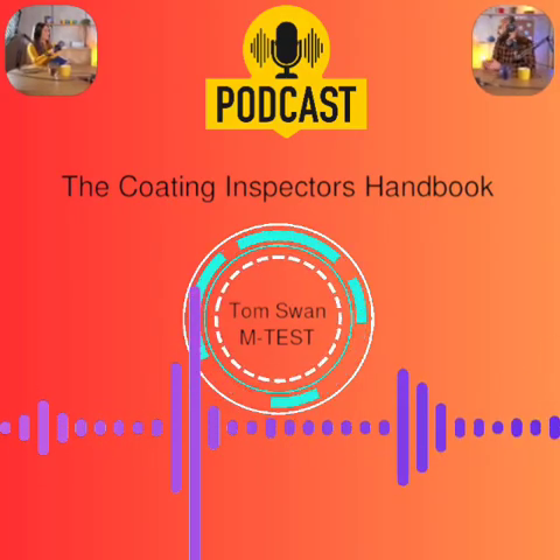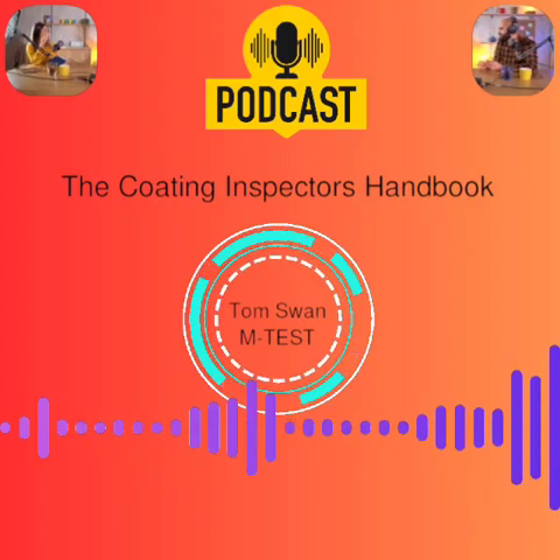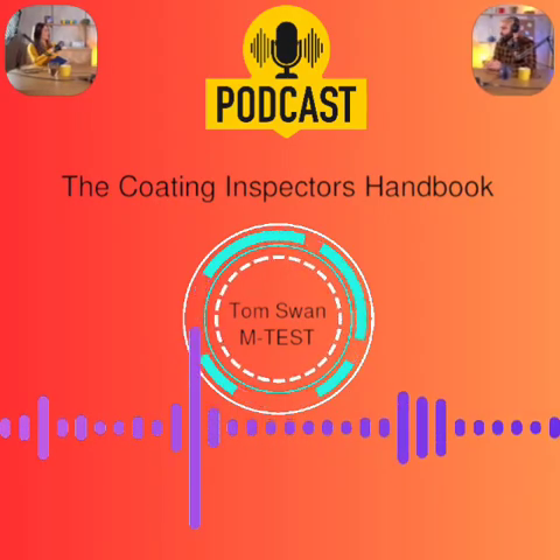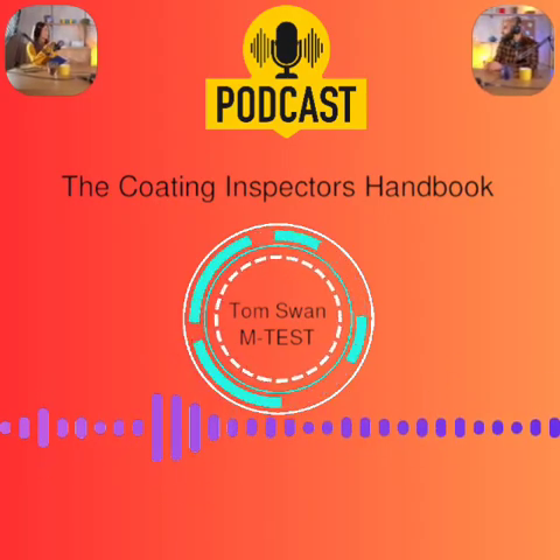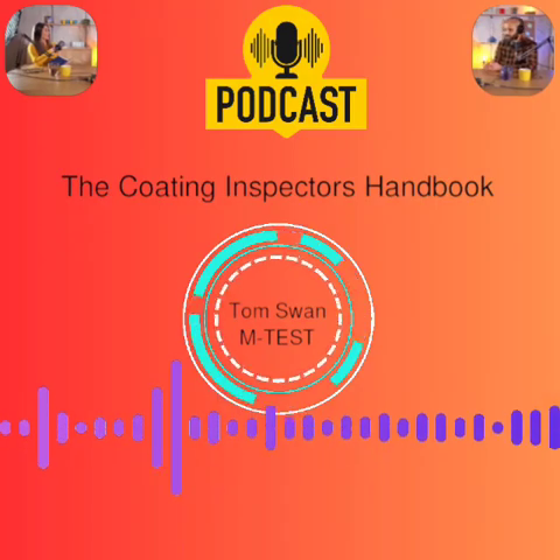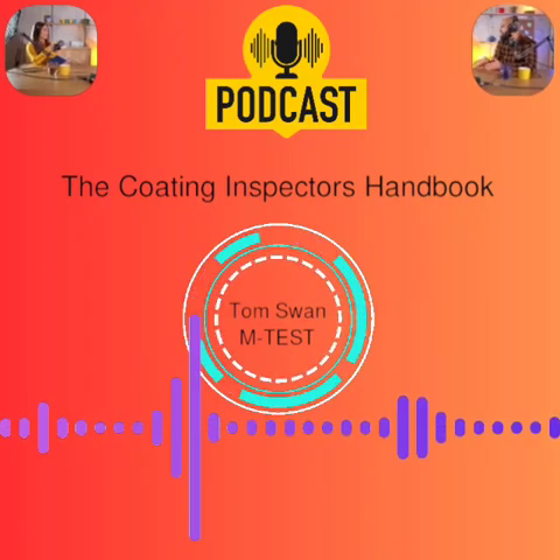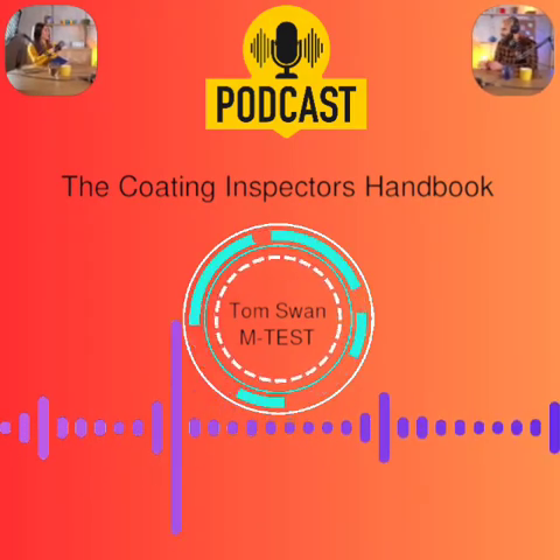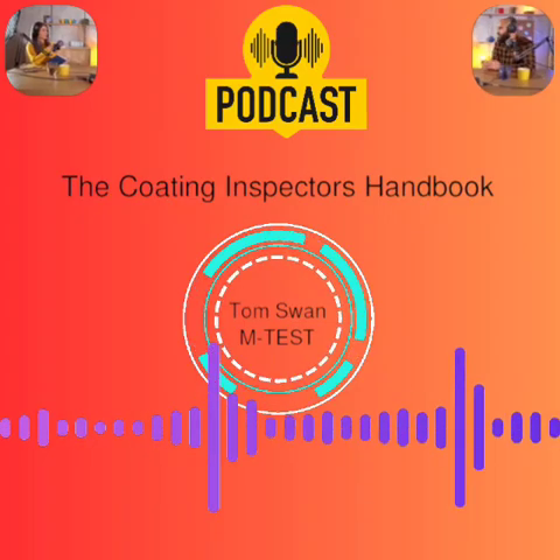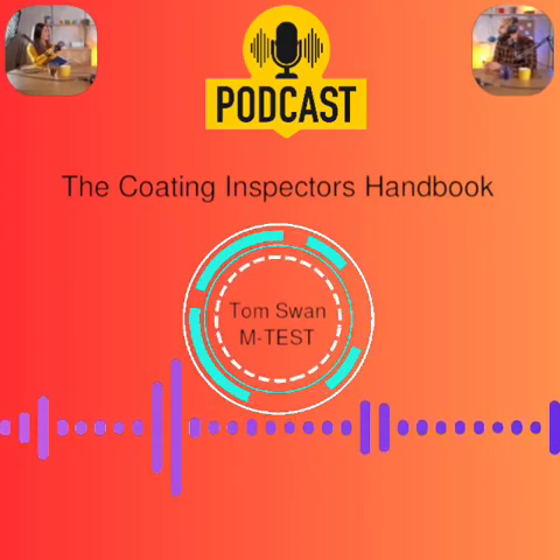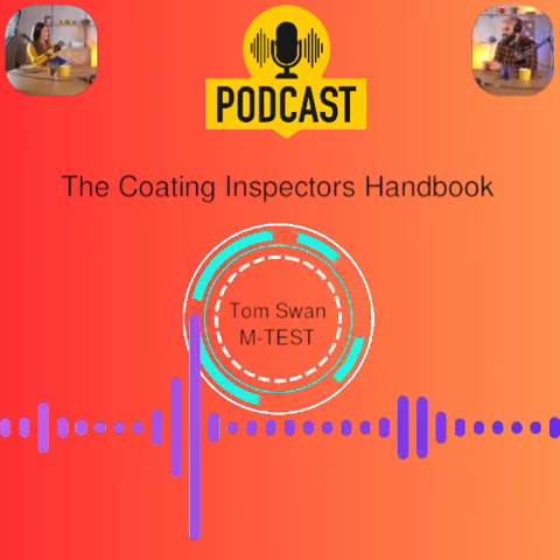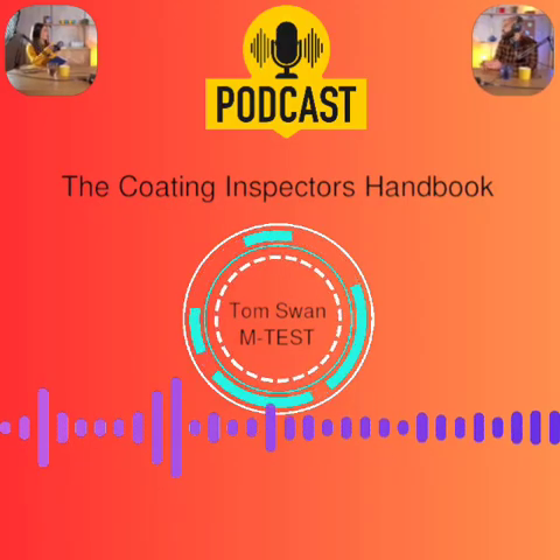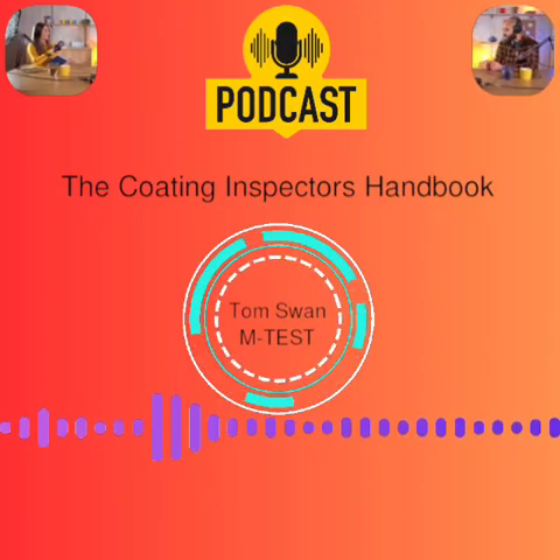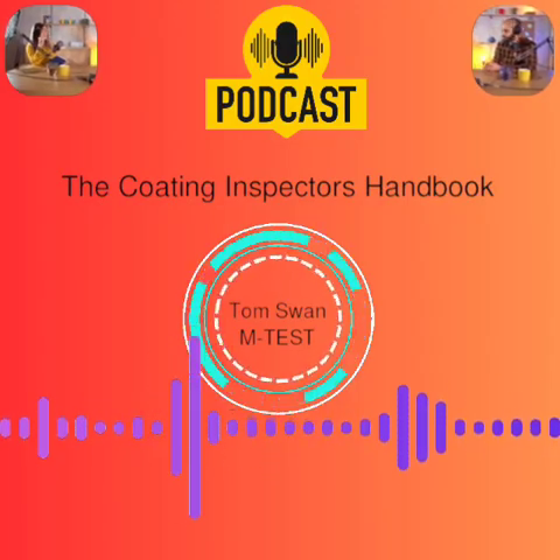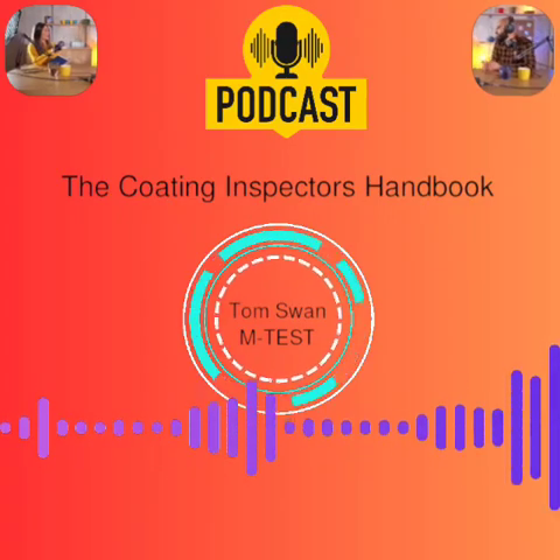It conforms to standards like ASTM D6132, ISO 2808, SSPC PA9. Limitations: the coating usually can't have aggregate. There are thickness limits; polyurea, for example, absorbs the sound signal. Substrate evenness is huge. Concrete variations can be bigger than the coating thickness. What if readings are weird? Could be false echoes. Use high and low gates on the meter to filter signals outside the expected range. Take lots of readings and average them. Use couplant gel.